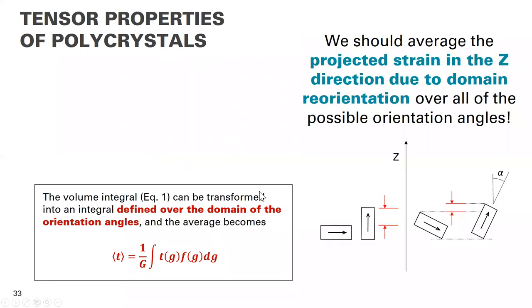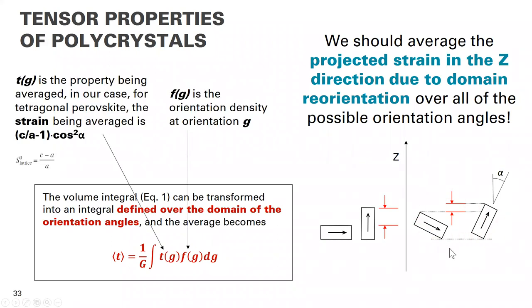Now, what does this mean for us? We mentioned that these other orientations contribute to strain, and we must account for that somehow. And so these two terms shown in this fundamental texture equation represent f of g, which is the orientation density, how strong is that orientation density, and t of g, the property being averaged. And in that case, for us, it's the spontaneous strain multiplied by cosine squared of alpha.